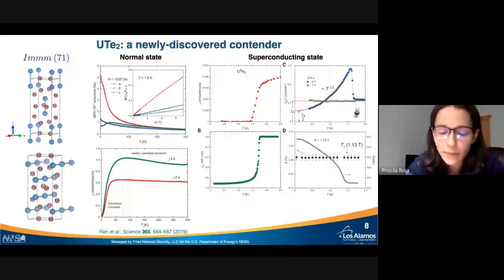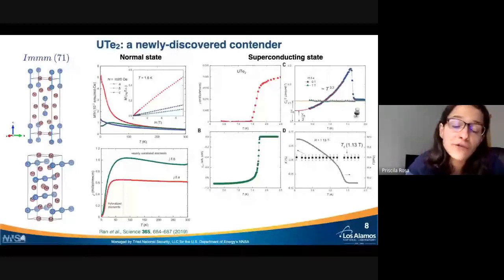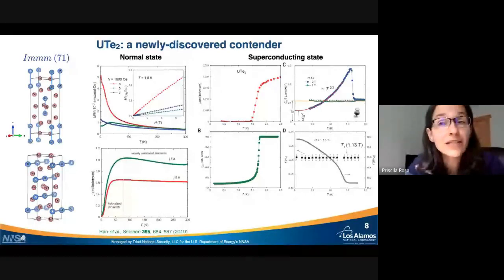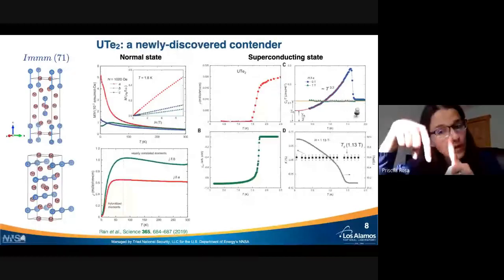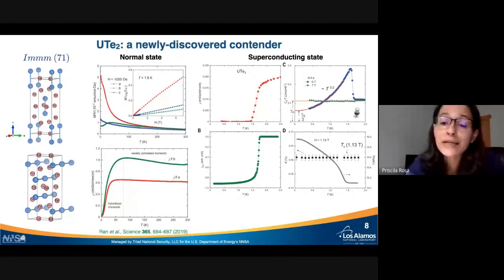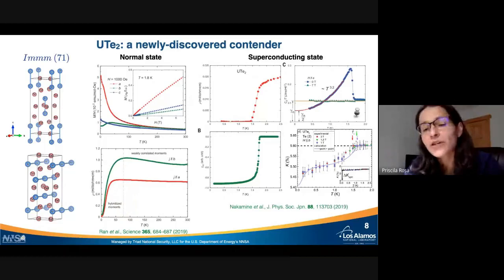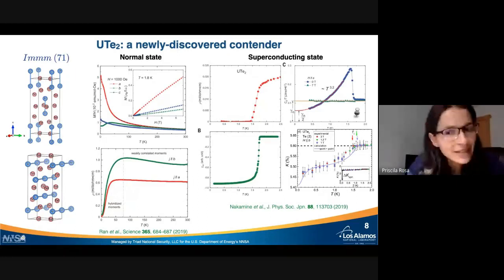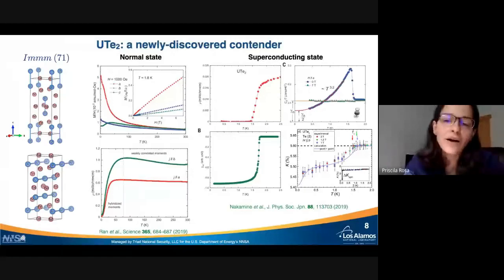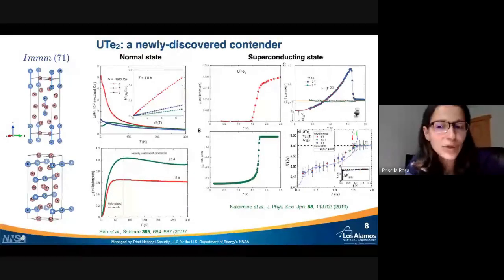NMR measurements, or nuclear magnetic resonance measurements, do not show any change of the Knight shift through TC, and this is a pretty good indication that this is not a spin singlet material, because if it were a spin singlet material, the Knight shift should go to 0 at 0 temperature. But I should mention that more recent results actually show a small but measurable drop, and this could be related to the superconducting d vector of this possible spin triplet superconductor.